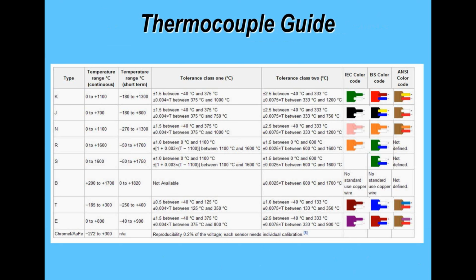Now in terms of thermocouples, you have lots of options. However, the majority of profiling systems on the market use a K-type probe. And the K-type probe covers the temperature ranges that generally we use, and you should not use another type because that may affect the calibration of the profiler you're actually trying to use. In fact, it will. So just use the thermocouples as supplied, or as specified for your particular unit. Otherwise, error can occur.